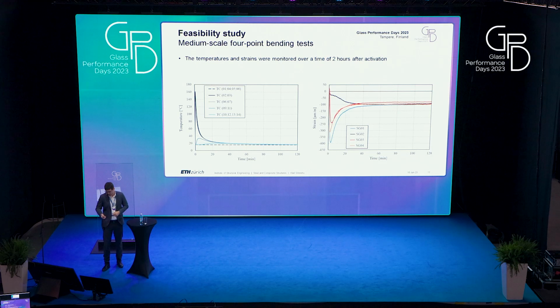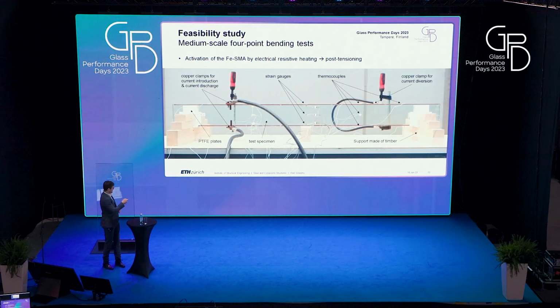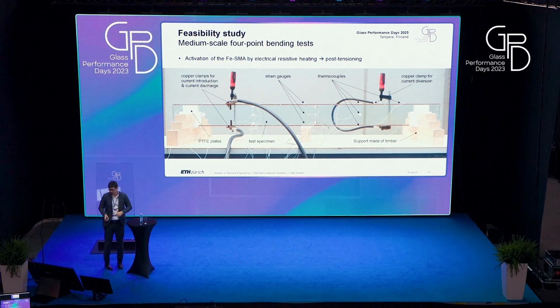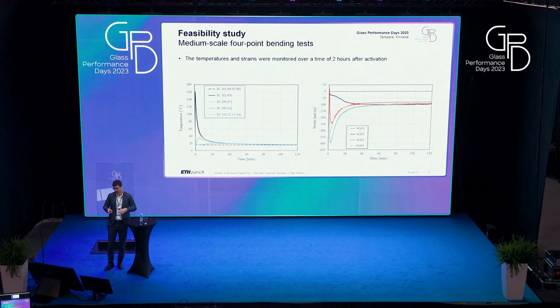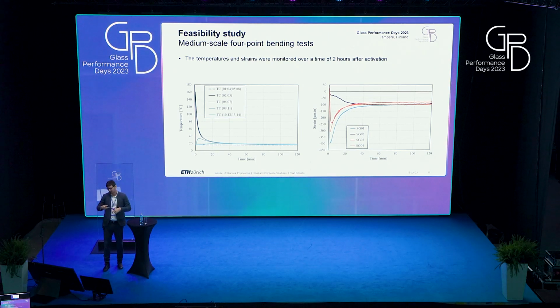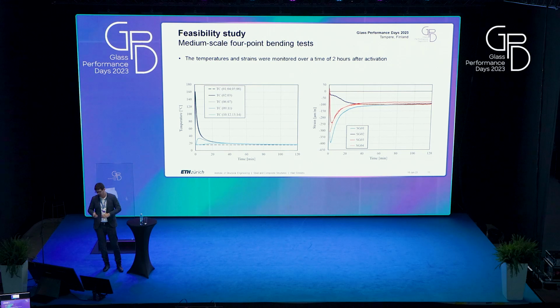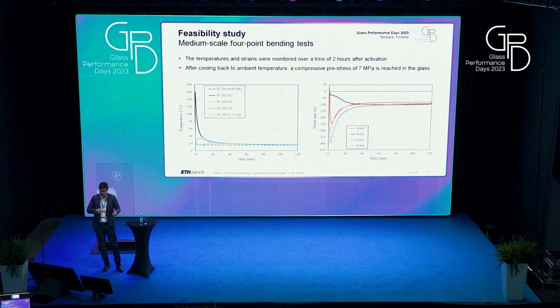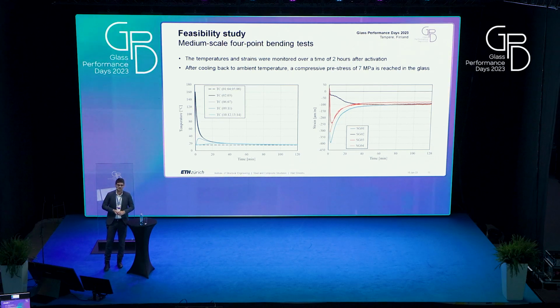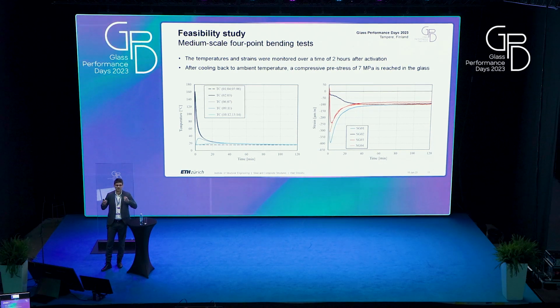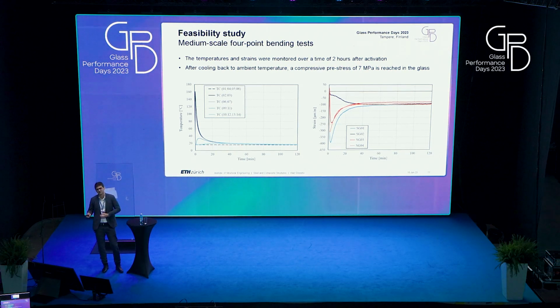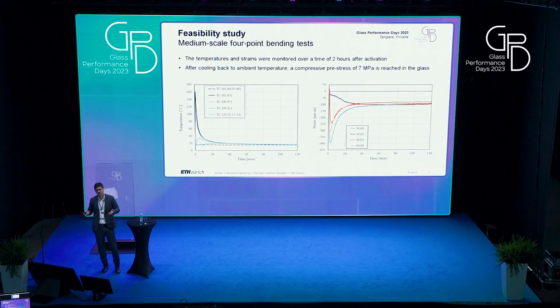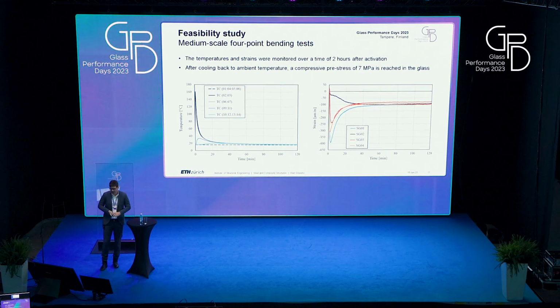Looking at the strains, we had strain gauges over the height of the beam. In the beginning of the activation, the strains were not uniform, but over time, after it cooled back to ambient temperature, we had a uniform strain corresponding to a compressive pre-stress of around 7 megapascal. I have to say that we applied the electric current to reach a target temperature in the shape memory alloy strips, defined as 160 degrees in this case. You could increase it further theoretically, but then you really have problems with the adhesive there, so it's a compromise.